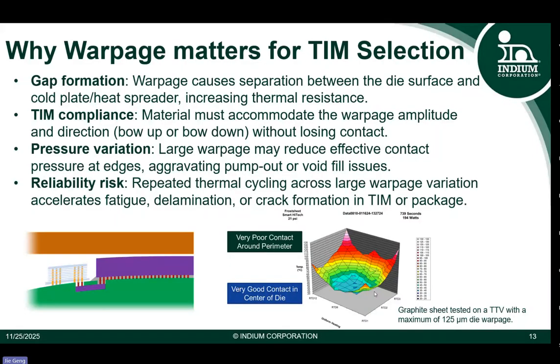Here is an example of testing on the thermal test vehicles. It's a graphite sheet test on a TTV, which has a die warpage of 125 microns. You can see at the 4 corners, the temperature is much higher than in the center. That's because the warpage causes a gap between the die and the heatsink, and the TIM materials lose contact at the surface, which increases the temperature very much.